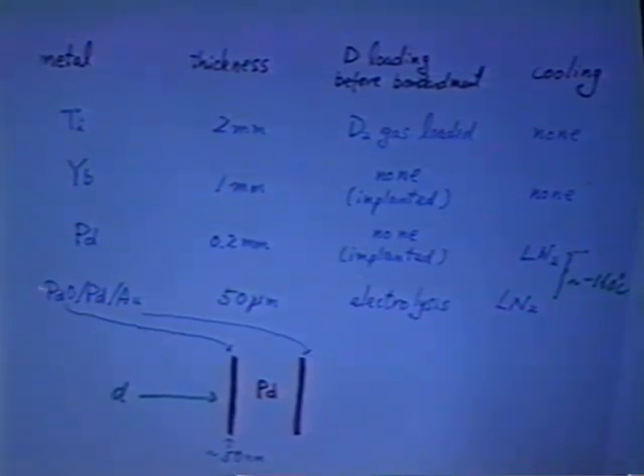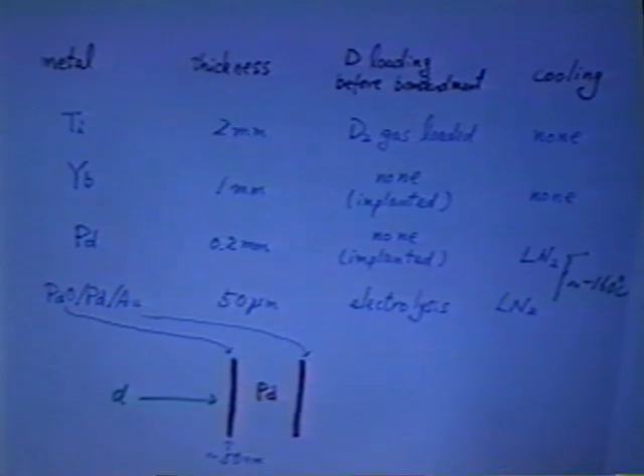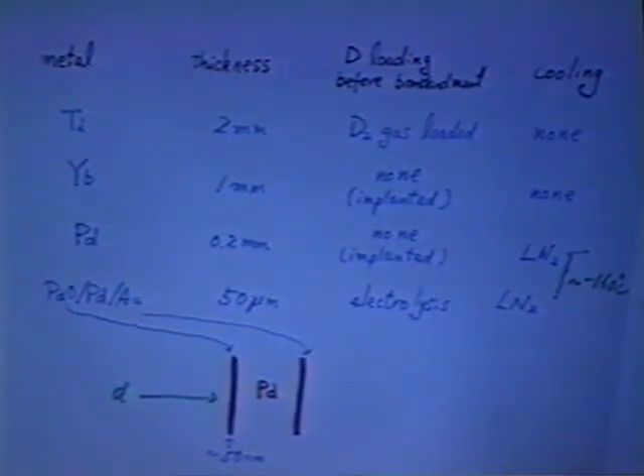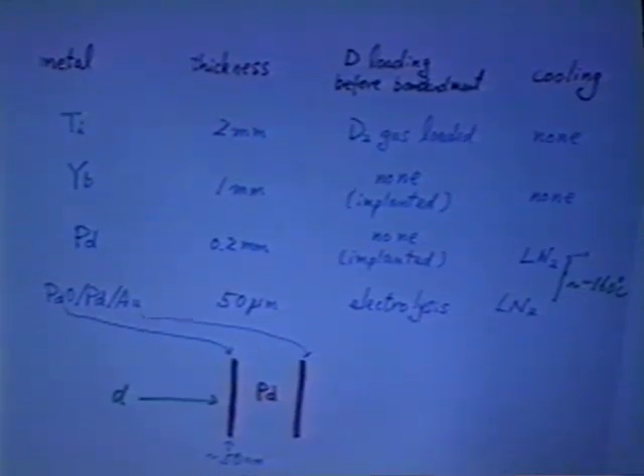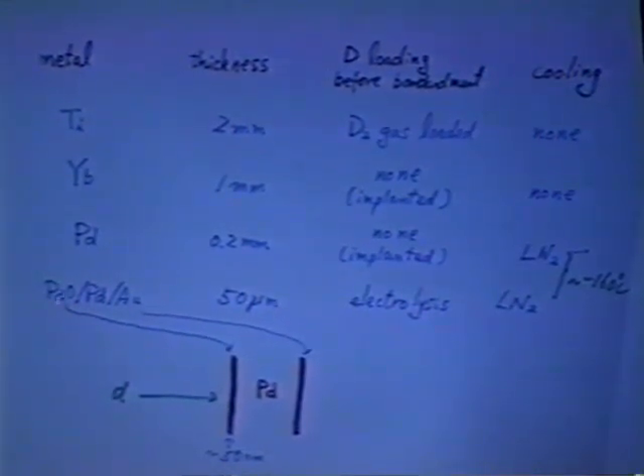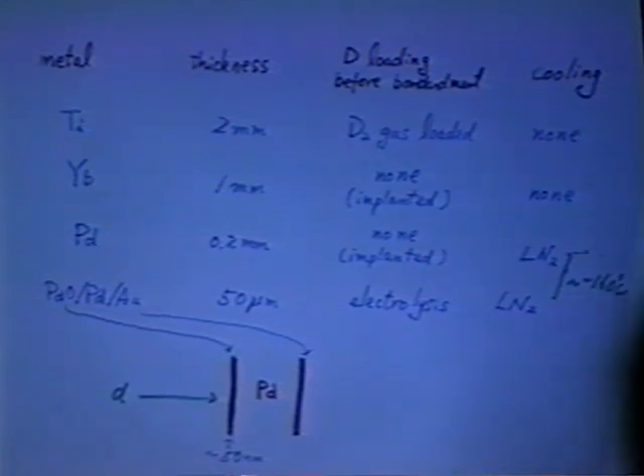And then for this one, this is a palladium oxide, palladium gold, brought by one of my colleagues from Russia, Dr. Lipson. In this case we did electrolysis to charge, to load the deuteron. And those targets were cooled down to minus 160 degrees. For this target, we bombarded this side, the palladium oxide side, so the beam is coming this way, and the thickness of this palladium oxide layer is about 50 nanometers.